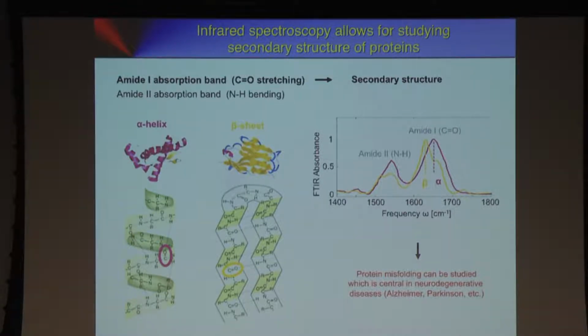It's rather important to understand these folding processes, and it would be interesting to study them on the nanometer scale. This is difficult to study. However, infrared is a very interesting probe for this. Here you can see the infrared spectrum of the so-called amide 1 band for alpha helical structure and for beta sheets. This peak traces the C=O double bond in both cases, but because of the different secondary structure, we have a huge shift of about 10, 20, 30 wave numbers.